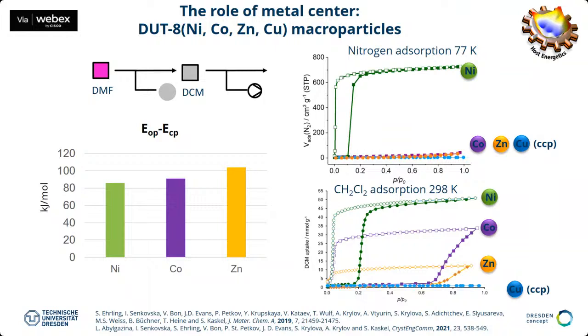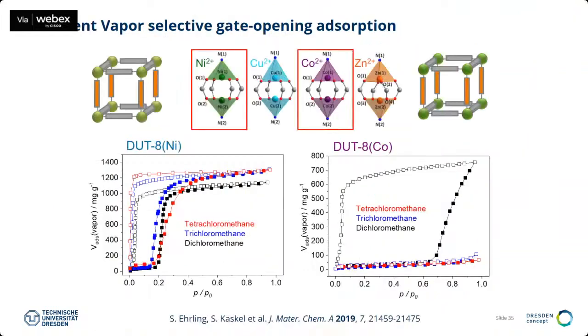When you use a more powerful adsorbent, a molecule which can push the pores open because it's solvating the inner part of the structure, like DCM, which is a more powerful solvent because it has stronger interaction with the pore walls, then you can see this subtle interaction much better. So the DCM can easily open the nickel MOF, but for the cobalt MOF, for example, you need higher energy, basically a higher saturation pressure, to open it, and you also cannot open it completely. You don't reach the same saturation. And for the zinc, because the energy difference is even higher, it is even more difficult to open the structure. So this allows you now to rationalize with this model system how responsivity works. The metal cluster really regulates the selectivity in this case.